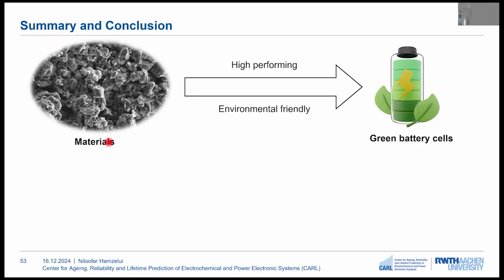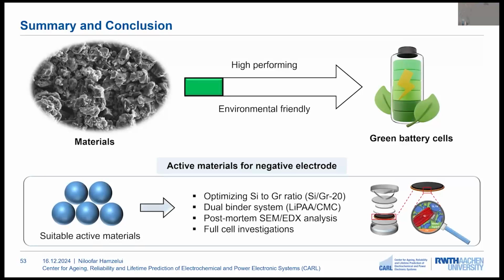So as it was mentioned in the motivation slides, in this work I have investigated the materials on the anode of the battery to have high performance and environmental friendliness, so that we can move towards green battery cells. In the first section, active materials were investigated. Silicon-graphite electrodes were optimized, and it was seen that 20% silicon shows the optimum performance. A dual binder system of lithium polyacrylic acid and carboxymethyl cellulose was used, and postmortem SEM-EDX analysis was performed on the electrodes to observe the degradation after electrochemical cycling, as well as the full cell investigations.